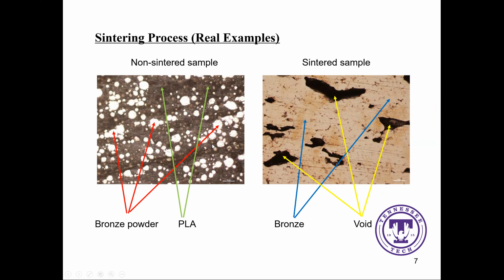These are some real examples. The left is the non-sintered samples. We can see the bronze powders in the PLA matrix. After the sintering, the final part is pure metal, pure bronze, but we have some internal void here. By changing the manufacturing parameters, like the layer thickness, the raster ratios, and the sintering temperature, we could minimize the size of the internal void, but it cannot be zero.